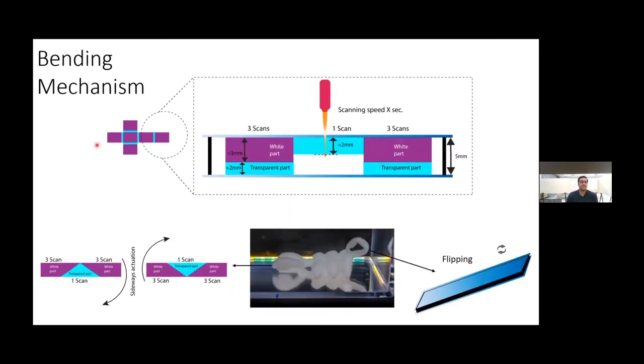Using this technique, we can create, as I have shown at the beginning, the video of the box. This purple portion you can create using 3 scans. Here will be the approximately 3 millimeter white part and 2 millimeter transparent part. And for this purple portion, you can use a similar technique. For the hinge, you can use only 1 scan and create an approximately 2 millimeter thickness hinge. For the scorpion, you can see the tail is going upside, so you can just flip the mold and print in a similar way.